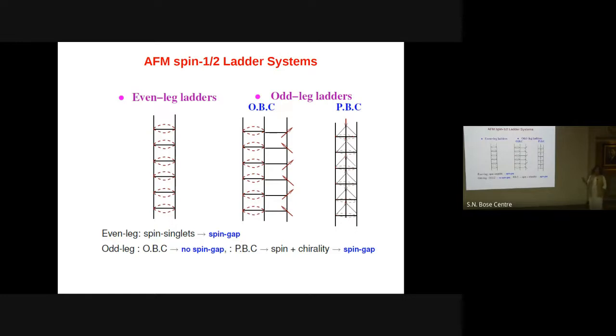But the tube, you can actually think, you can cut it, and you can think in terms of an odd leg ladder, because I actually had 9 vanadiums, I didn't mention it, 9 vanadiums in this ring. So it's an odd leg ladder, but with a periodic boundary condition. I can think it's a closed ring, so it's a ladder if I can close this ladder with a periodic boundary condition. If you do that, then in addition to spin, you have a degree of freedom, which is chirality, because since I have closed it, I can go either in this direction or in the other direction, and that should actually give rise to spin-gap. But this system doesn't show any evidence of spin-gap.